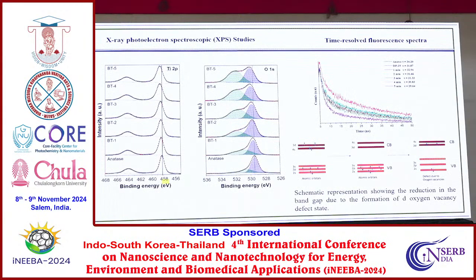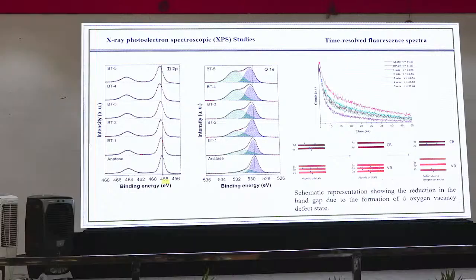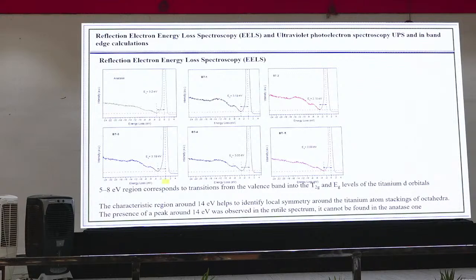We have even done the time resolved spectroscopy, just to know at what particular level that band gap, that vacancy, that band gap has been formed. Then we have done the reflection electron energy loss spectrum, which we usually call EELS, which is very much appropriate to calculate the band gap, not the regular UV. So when we have defects, we usually go for this kind of analysis.